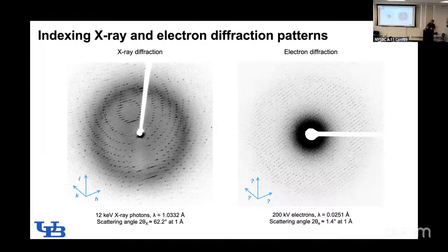What this means is it's very, very difficult to figure out where you are in reciprocal space from a single still. With X-rays you can index one diffraction pattern, and you take all of these stills and index them without knowing what the unit cell is. In electron diffraction, unless there's something I don't know, I don't think that's possible. You don't know where A, B, and C, your unit cell axes, are. So you do have to have a wedge, or at least a few different images at different tilts, to figure out where you are. This is actually a challenge in electron diffraction, now that we're starting to go to scanning techniques and high throughput things like this.